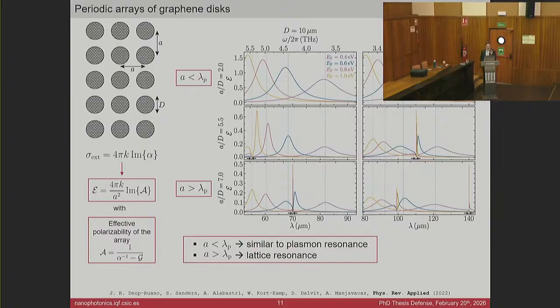We compare our really simple model, which just models each particle as an electric dipole, with finite element method full wave solutions of Maxwell equations, with really nice results in both regimes. You can see that there is a really good match. And by comparing the left and right panels, we can realize something really interesting. We can see that the peak extinction efficiency in left and right is the same.